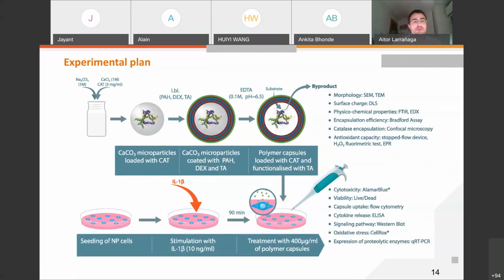So to fabricate these capsules, as I said before, we follow the layer-by-layer approach. First of all, we fabricated our sacrificial template. In this case, our sacrificial template were calcium carbonate microparticles loaded with catalase. This is a very simple process. It is called co-precipitation process, in which you simply mix a sodium carbonate and a calcium chloride aqueous solution in the presence of catalase. So the catalase, in this case this enzyme, will be entrapped within these calcium carbonate microparticles.